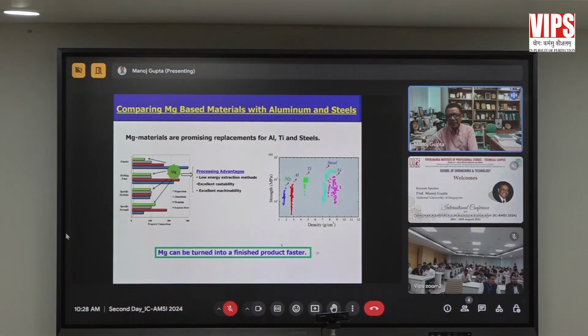Now let's compare magnesium with the workhorses of metal like aluminum base alloys, titanium base alloys, and steels. If you look at the graph on your left hand side, you see that magnesium has the lowest density, it has one of the lowest melting points, and it has similar specific modulus and specific strength next to titanium, but titanium comes at 5 times the cost.